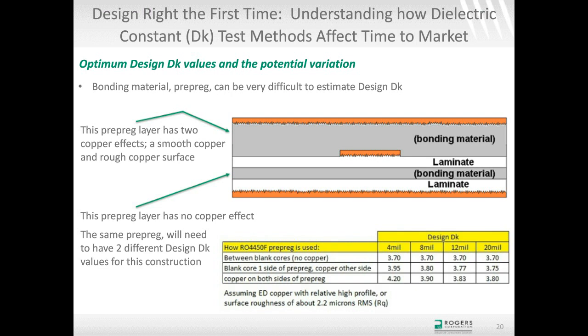And here's an example where a stripline circuit is made up of a combination of laminates and prepregs or bonding material. And the prepreg that's on the bottom layer between the bottom ground and the signal layer in the middle, that prepreg layer is not affected by copper effects. So there is no copper effect as that prepreg would perceive it. And that means you should really use the design Dk, which is the intrinsic dielectric constant of the raw material itself. And using that exact same prepreg on a different layer in the circuit, you would actually use a different number for design Dk. And that's the bonding material on the top side.